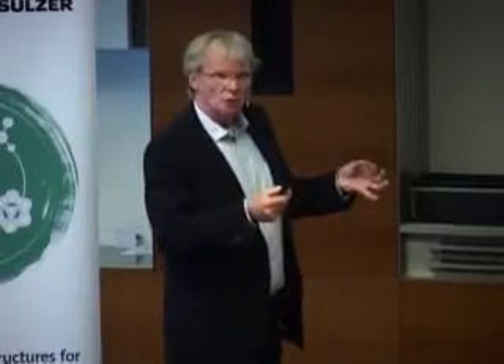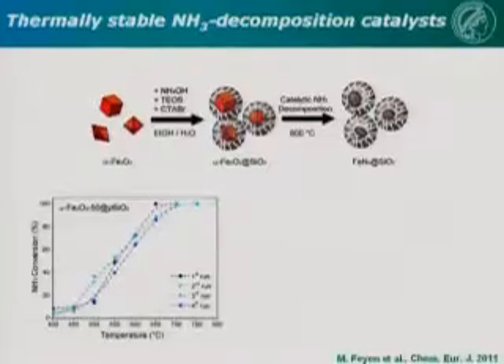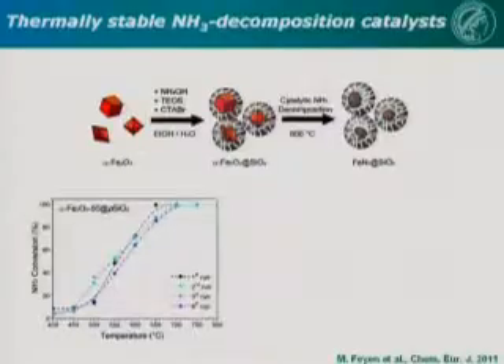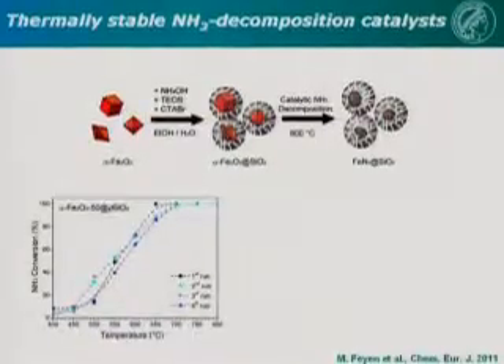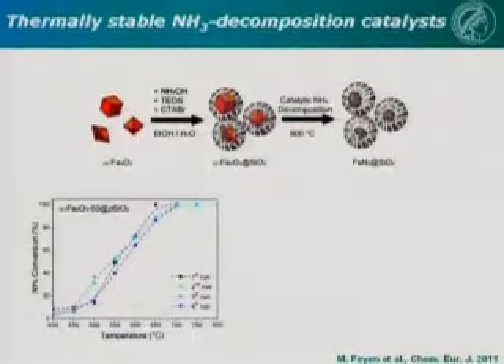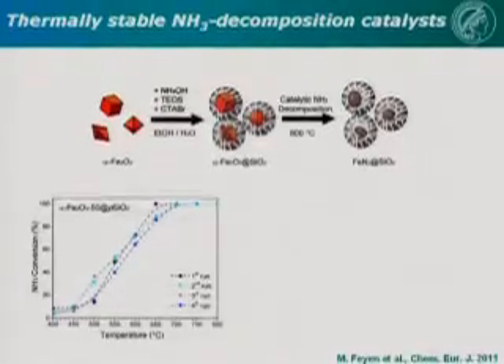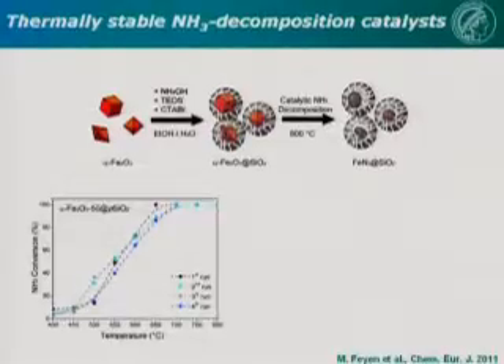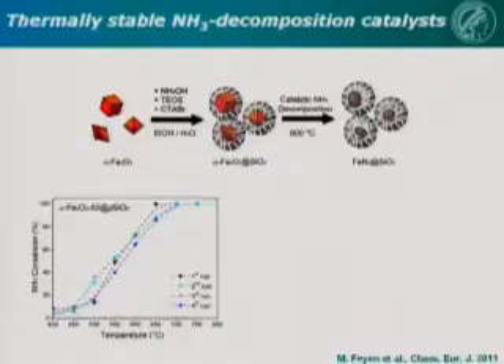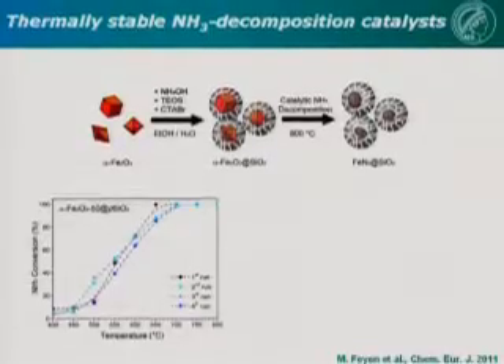And if we run then catalytic ammonia decomposition, again for generation of clean hydrogen, the iron oxide is converted to iron nitride species, different types of iron nitrides. And this is a pretty nice and active catalyst, actually more active than the one I have shown you before, and it's stable. And the reason why it's stable is that we have encapsulated this iron particle in the porous silica shell so that 2 iron particles will never meet each other and can never sinter together.